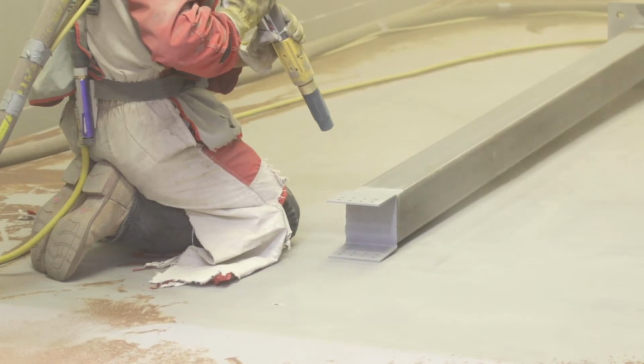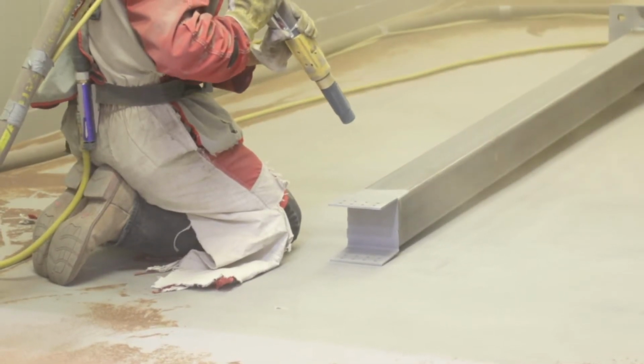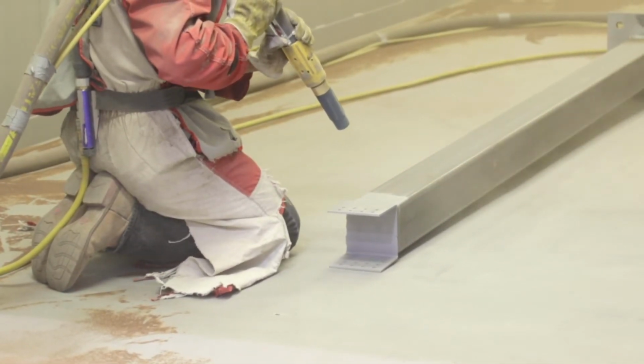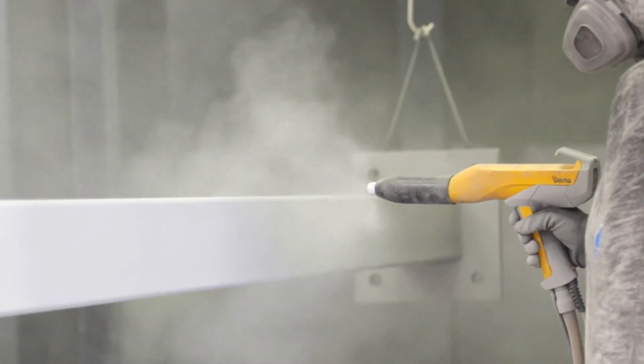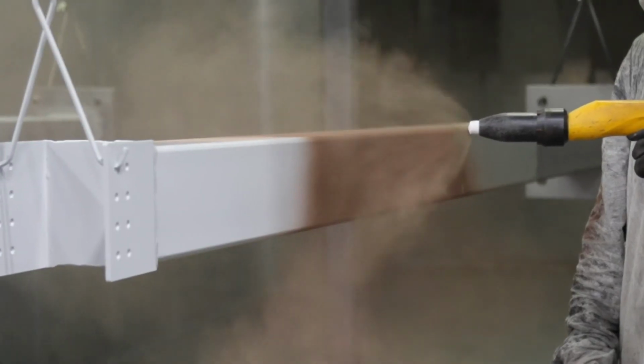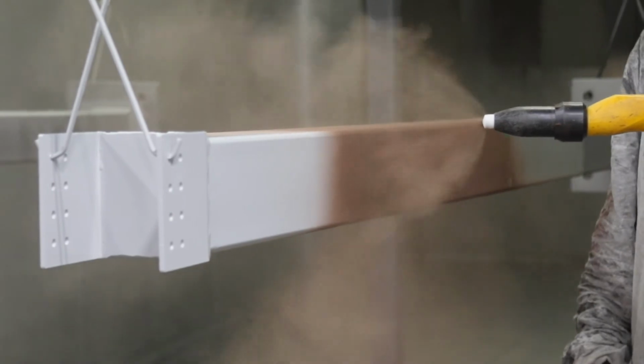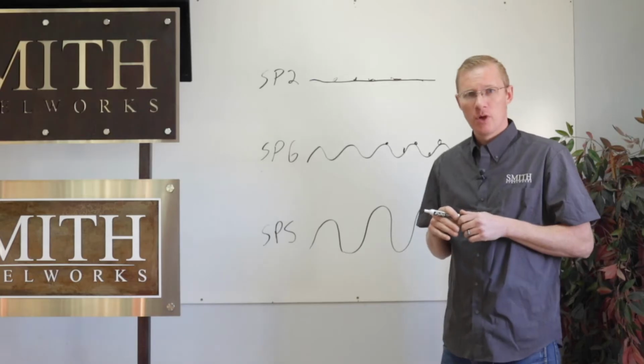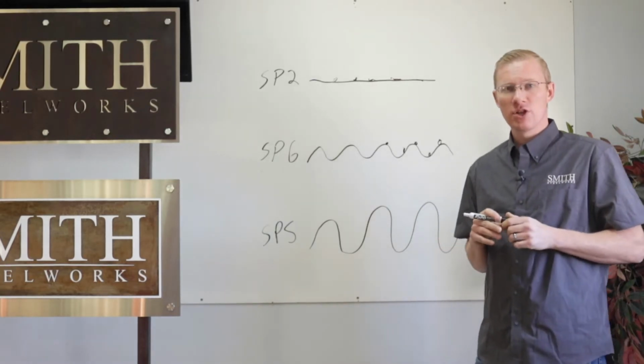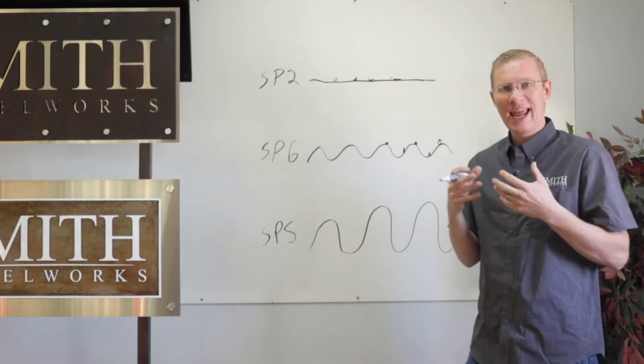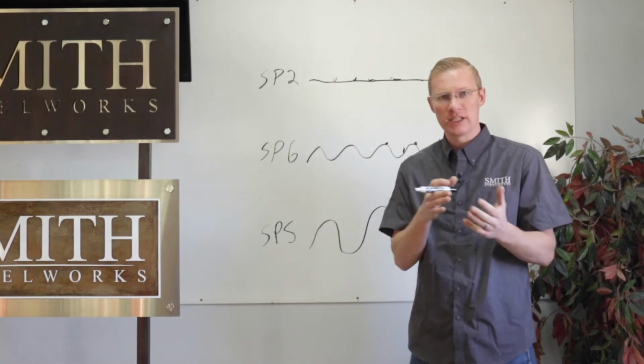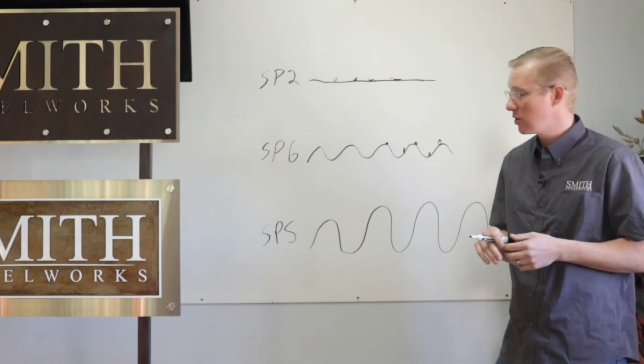In order to achieve an AAMA 2604 or 2605 standard, the process that needs to be followed is sandblasting to SSPC SP-5 NACE white metal finish, primed with the small molecule epoxy primer, and powder coated with a super durable TGIC polyester top coat. When powder coating, it is recommended to use a small molecule primer to enhance that mechanical bond between substrate and powder coat top coat.